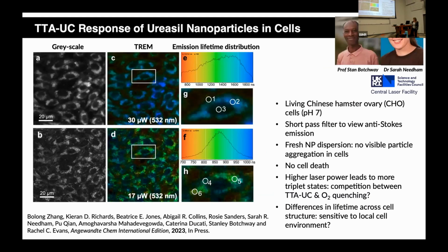We reached out to Stan Botchway and Sarah Needham at the Central Laser Facility in the Rutherford Appleton Laboratory. I have to say, all of this was done during COVID, when all the labs were, it was really sort of shuttling samples around, and trying to be sort of Belong was very, very good at making things happen. So we did some imaging on cells. We'd never done this before. Sarah's the biologist, and first of all, we had to get the particles into the cells. So there was a lot of optimization of size and so on, but they do go in, and we saw no particle aggregation. We didn't kill the cells, so this was all very positive.